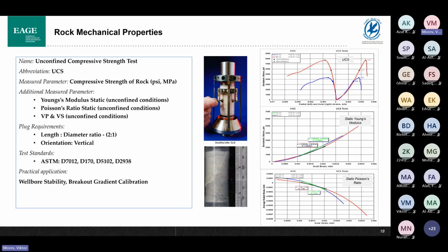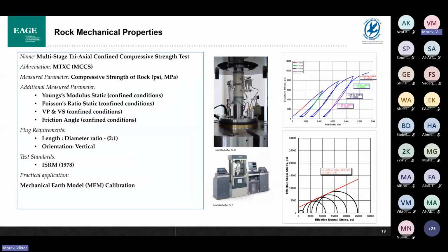For compressive behavior, however, the most familiar test is the UCS test. The UCS test measures the unconfined compressive strength of the rock, in other words, the peak strength of the rock. In addition, from the stress-strain response, we can derive static Young's modulus and static Poisson's ratio. The limitation is that subsurface rock is normally confined. So the next step is to look at the behavior under confining conditions, and we have a specific test for it. It's called the triaxial test.